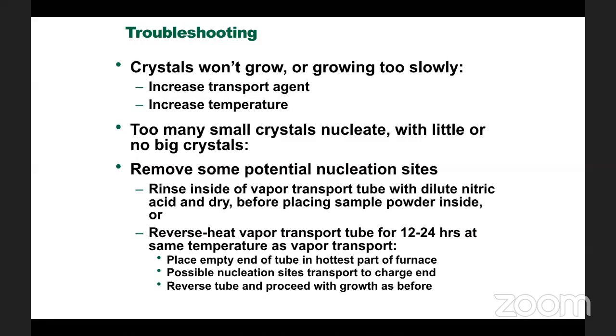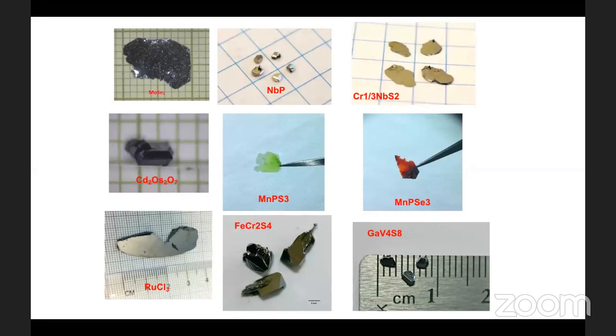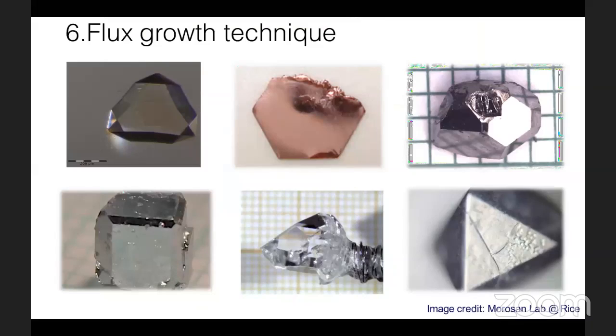Sometimes if the crystal is very small and not growing to a big size, then maybe some other phase may be formed. So in that time you can take the material and dissolve it in acid and make a very pure material. Then again you put that material in the quartz tube, and keep one side very hot and the other cold, instead of putting it the regular way. So you can make all the material go to one side, and you can grow it. So these are the materials which are grown in our laboratories.